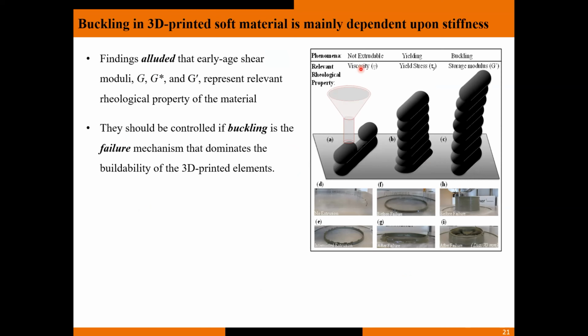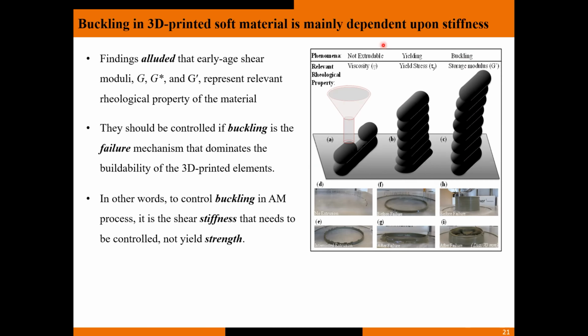And as you can see here, viscosity essentially controls the ability to extrude. Yielding controls the ability to avoid yielding failure. Once you build up, you really should be looking into the storage modulus or complex modulus to control buckling. Although these properties are interrelated, it's an important distinction as we scale up the processes in construction, as a means to tune the chemical characteristics of surfactants and other chemical admixtures specifically for 3D printing.